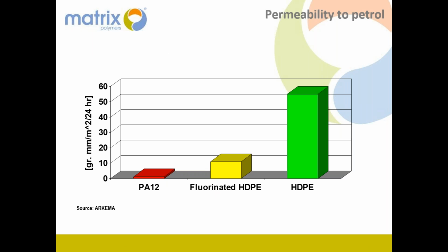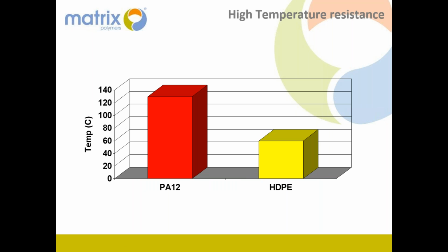So you can see the permeability with relation to other materials. This is essentially the amount of material that permeates into the fuel. So that's why the red, which is very, very low, is much, much better than a normal HDPE. This is grams per millimeter per square meter per 24 hours. It's essentially the amount of polymer particles that migrate into the fuel. That's what makes it suitable for petrol. Temperature resistance is of course much higher; it can easily withstand up to 125 to 130 degrees.